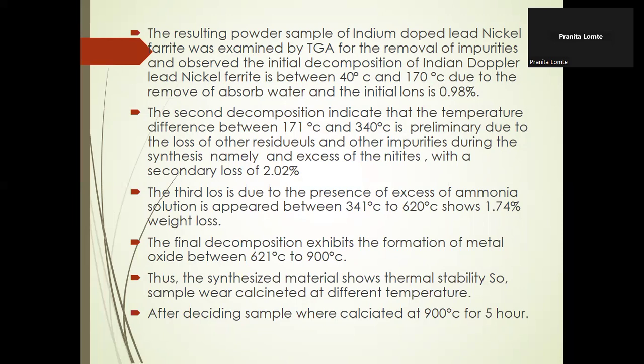The second decomposition indicates that the temperature range between 171 degrees Celsius and 340 degrees Celsius is primarily due to the loss of other residuals and impurities during the synthesis, namely an excess of the nitrates, with a secondary loss of 2.02%. The third loss is due to the presence of excess ammonia solution and appears between 341 degrees Celsius and 620 degrees Celsius, showing 1.74% weight loss.